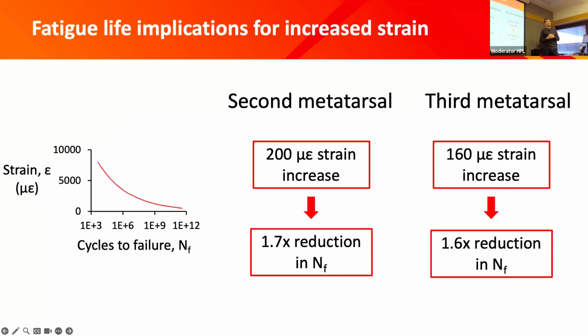All right, so we saw this cool change in strain happening at the second and third metatarsal in females, but what does that mean practically? What we can do is take that fatigue life data that I talked about before, and we can use that to show what the effect or factor of a change in strain has on the number of cycles to failure.